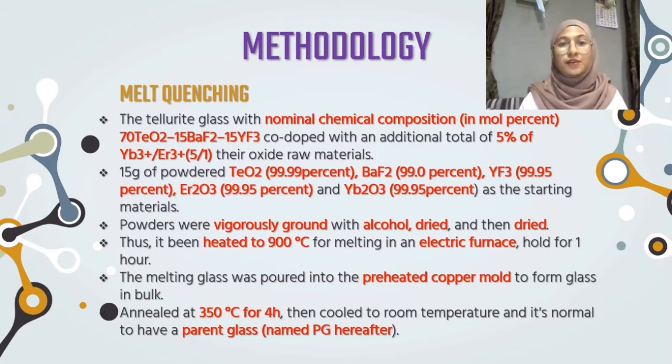as raw material, 15 grams of powdered tellurium dioxide 99.99%, barium fluoride 99%, yttrium trifluoride 99.95%, erbium oxide 99.95%, and ytterbium trioxide 99.95% as the starting material.